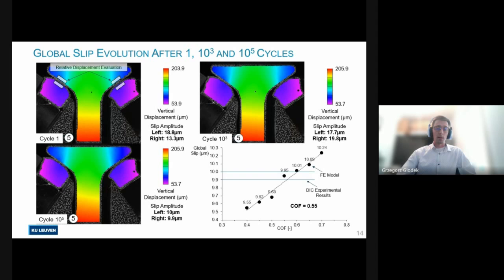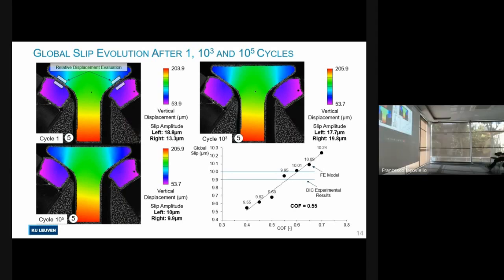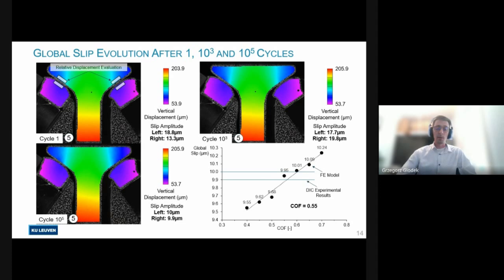And we can use those slip amplitude values to calibrate the coefficient of friction in our finite element model. So this was done by performing a parametric study with different coefficients of friction and extracting the displacements in the same region in very much the same way as in the DIC analysis. And that resulted in a coefficient of friction equal to 0.55.